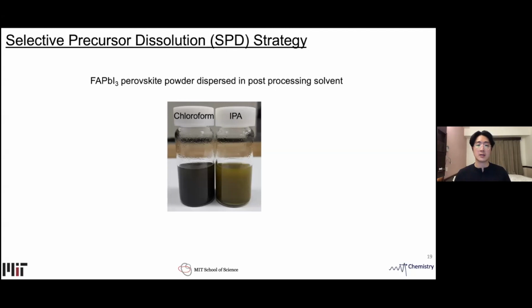On the right is the perovskite powder dispersed in isopropyl alcohol, the conventional method solvent. We see that for the IPA, the perovskite decomposes into its precursors, which are lead iodide and formamidinium iodide, where lead iodide has a yellow color, and also the delta phase, or yellow phase, also has a yellow color.